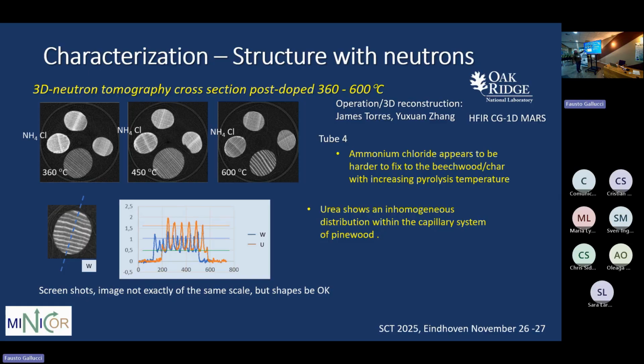And what you can do is a density analysis along the radius here, and a very interesting feature is that where you plot it, you see for the dark regions, there's very low difference between the doped and non-doped. So all the doping seems to be concentrated in these white bands, which correspond to the narrow capillary region, which is the late wood region, and this is the early wood region. So it shows an inhomogeneous distribution of the capillaries.